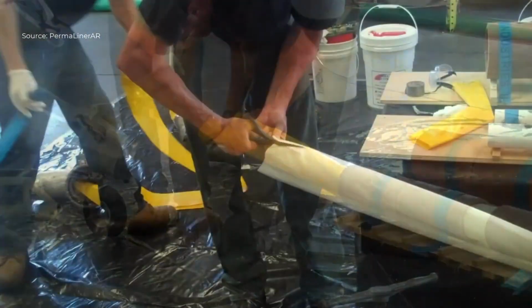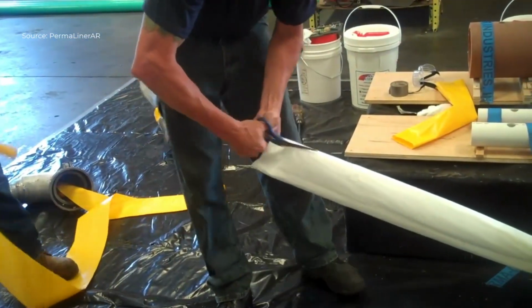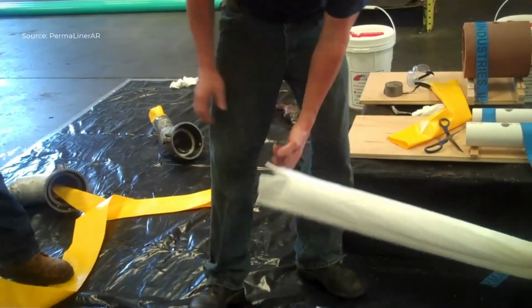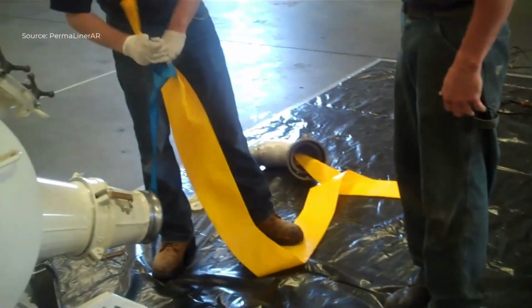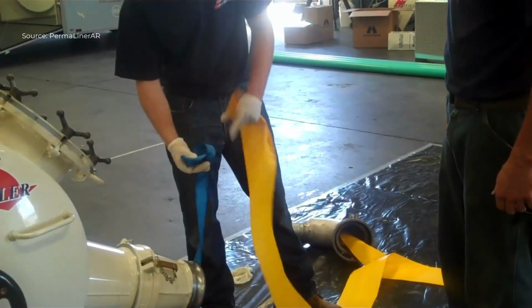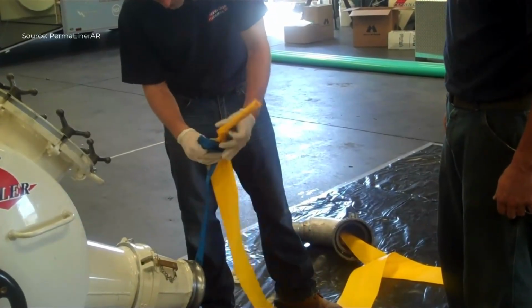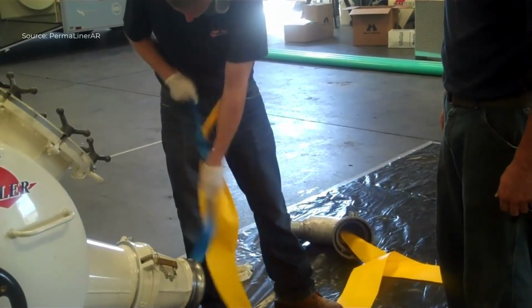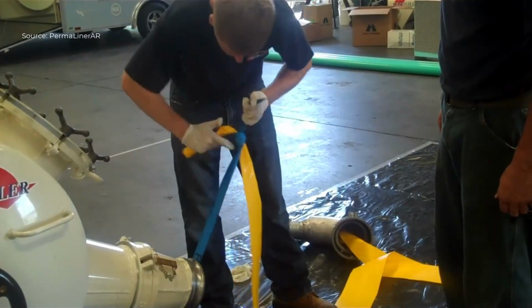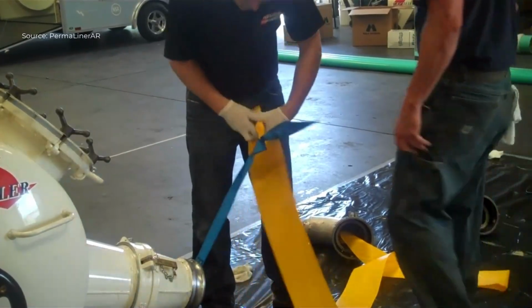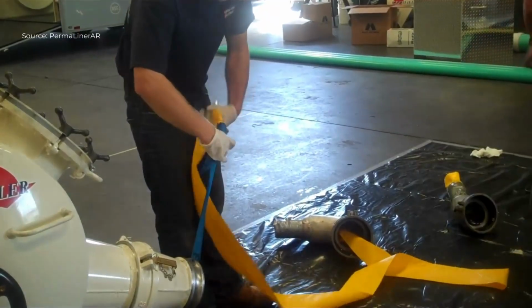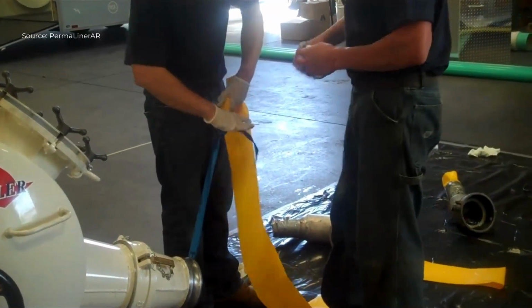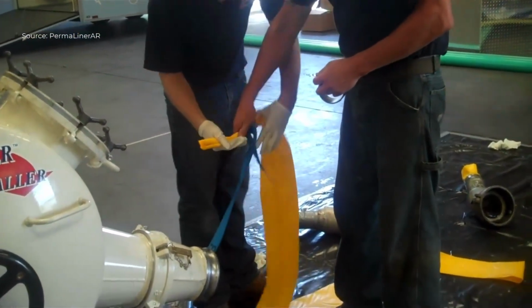Subsequently, the calibration tube is wound into the inversion unit, cam-locked, and fastened securely to ensure correct alignment. By gradually releasing the tube at approximately 8 to 10 pounds per square inch of pressure, the team achieves full expansion. Furthermore, this pressure squeezes out any groundwater infiltration that might be present in the pipe, forcing it out through cracks and joints and leaving the liner firmly in place.